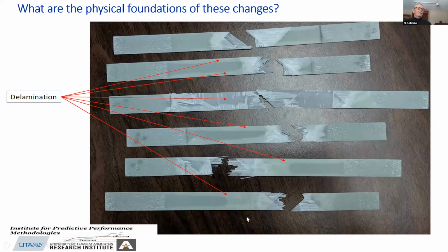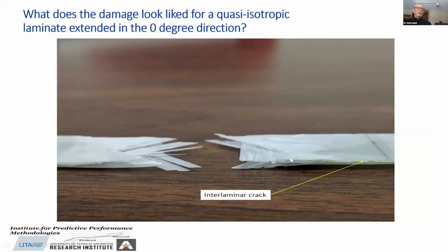But then we see a rather abrupt change to rather extensive global delamination before this thing fails and the fibers break. Now, the analysis we were looking at does predict fiber failure. So we should be able to see the fibers break in the analysis, but we are not able to predict this extensive delamination that goes all the way up the length of the sample in the specimen. And what does it do? It isolates, in these material regions, the top voltage plate from the bottom voltage plate. So the dielectric response drops rapidly because of that final event in the failure pattern.